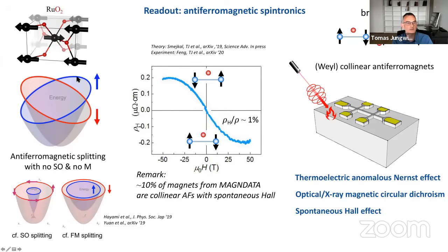Well, another remark that I like to make is that these collinear antiferromagnets which host the spontaneous Hall effect have a very peculiar type of spin splitting, which is nothing like the spin splitting we are familiar with from a spin-orbit coupled system or a ferromagnetic system. So you can have this large spin splitting even if you turn off spin-orbit coupling, and the spin splitting gives you a zero net moment, as you see. So this is a new type of spin splitting in electronic structure, which besides the anomalous Hall effect can also lead to many other phenomena yet to be identified and explored.